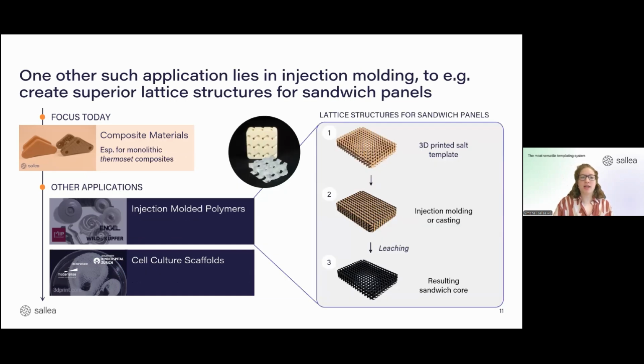And I want to show you an actual example for the second potential application. It is, for example, to still stay in the composite part, making a sandwich panel, and to make superior cores for such a sandwich panel that is often used in the aerospace or in the space industry. And how this is done is basically the same way. So we still 3D print a template. In this case, that can be a lattice. It doesn't have to be. Then it can be injection molded with quite high pressures and temperatures. Then it's solidified, and then again, the salt core is washed out, resulting in such a lattice core.